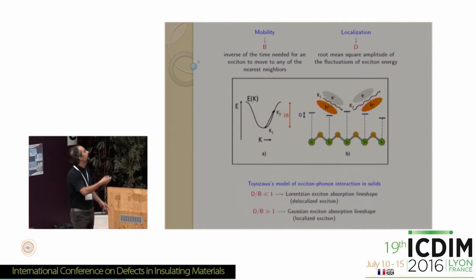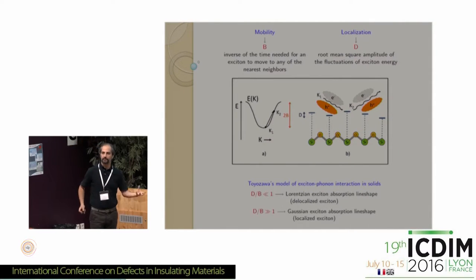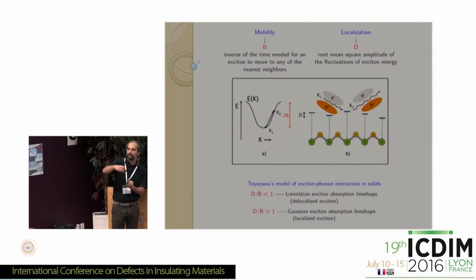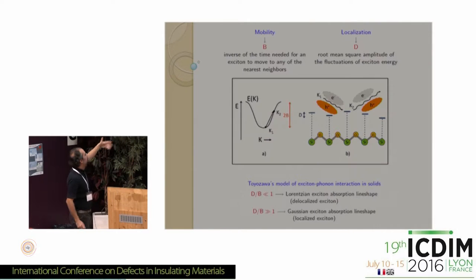There are two extreme cases. If B is much larger than D, meaning that the fluctuations are small or the mobility is very high, then the fluctuations do not hinder the inherent mobility of the exciton, and the exciton remains very mobile and delocalized, meaning that the excitonic states are delocalized and the exciton is fully mobile. Otherwise, if D is much larger than B, the inverse situation, it means that disorder is so high as to completely cancel the mobility of the exciton. The exciton becomes localized, no longer capable of moving from site to site. So these are the results of excitonic theory by Toyozawa, who recently retired, I believe.